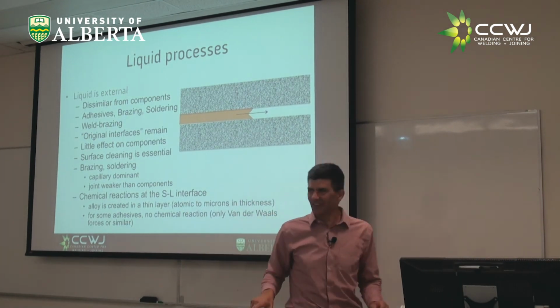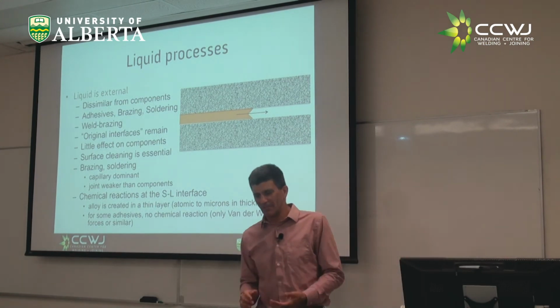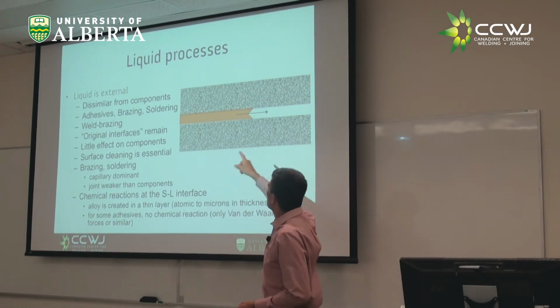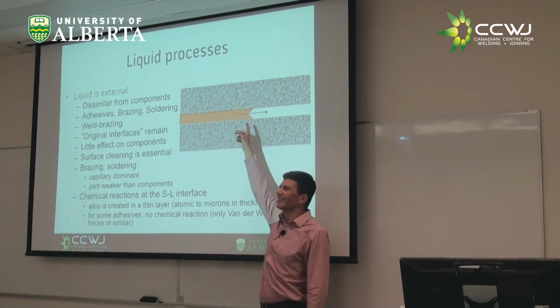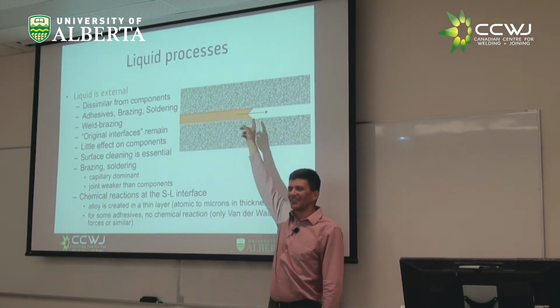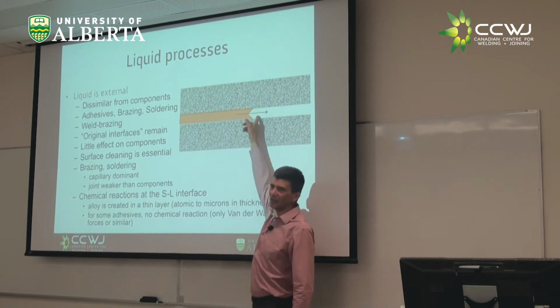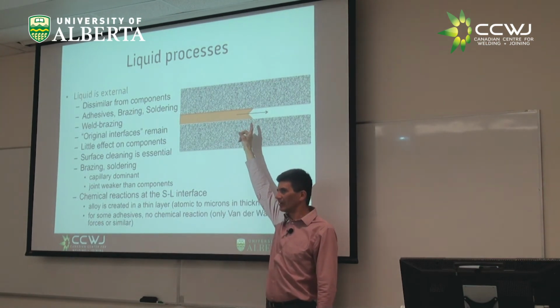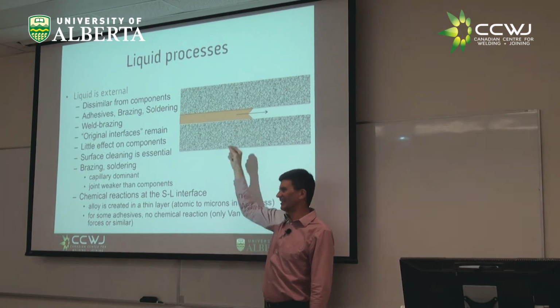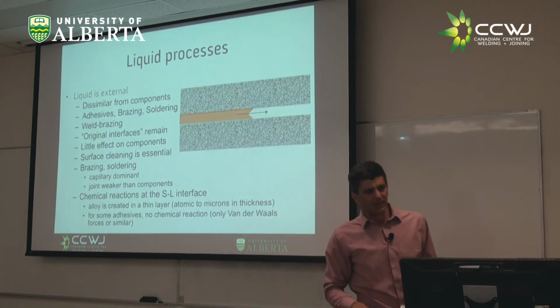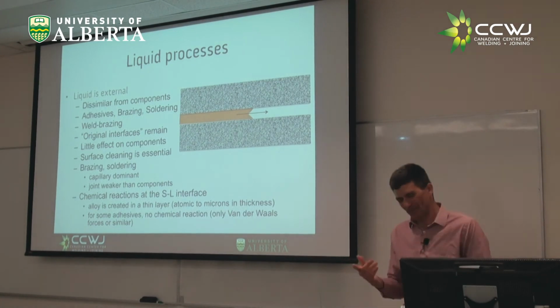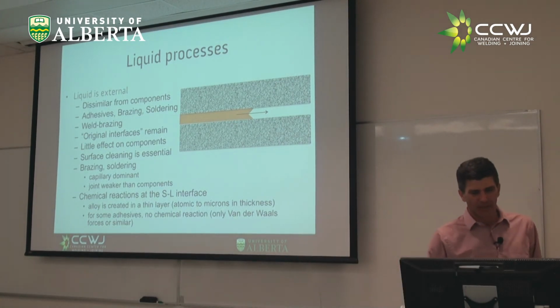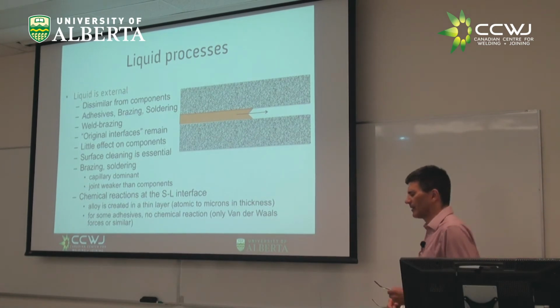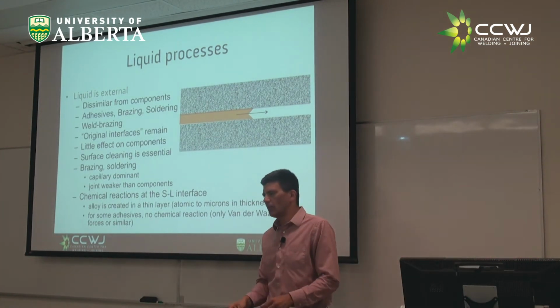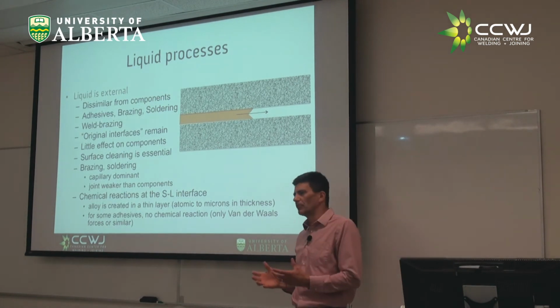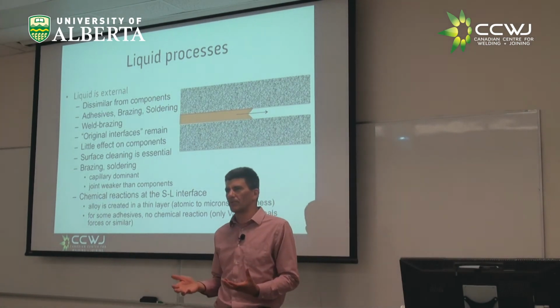All right, I don't need to teach anymore. That's exactly right. All my life I thought the bigger the gap, the better. But not true, because the capillary forces are higher with the smaller gaps, right? Assuming you have a wetting angle. But if the part is dirty, you might have a non-wetting angle, and then you're never going to get it in, right? So unless you make a huge gap. But if you make a huge gap, then it's not going to be a good joint.